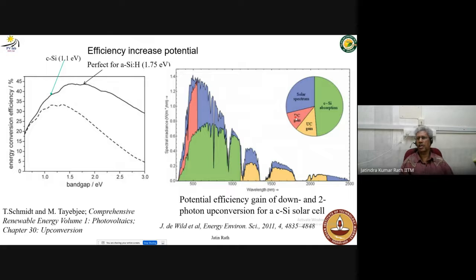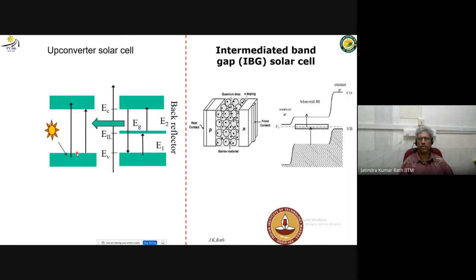I told you already that down conversion we tried that. The principle is okay, but you don't get that much. So here also a calculation was done. If you put up conversion material on crystalline silicon, you don't gain much, only this much. But for an amorphous silicon solar cell, you can gain tremendously. You can use the up conversion material, so we tried to do that.